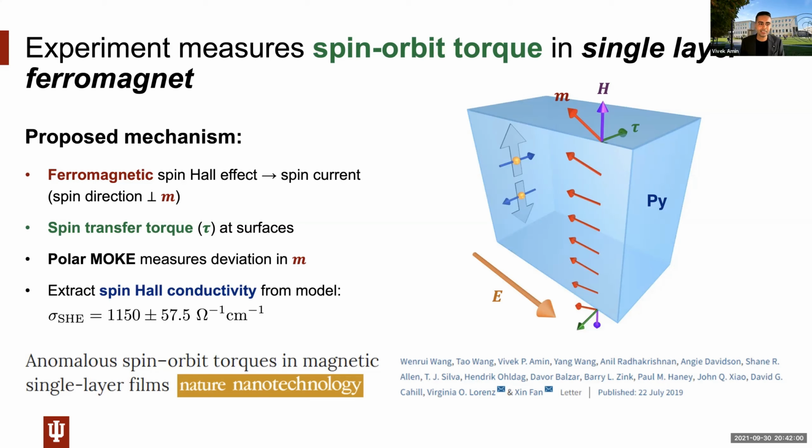So what this tells us is that we do have spin current generation in ferromagnets, or at least a torque that is arising, that is equal and opposite at the layer boundaries. So the exciting thing about this is not only does this say ferromagnets can contribute to their own torque, if you can create enough asymmetry in the material, you could change this torque from this torque and actually result in a net torque for the whole system.